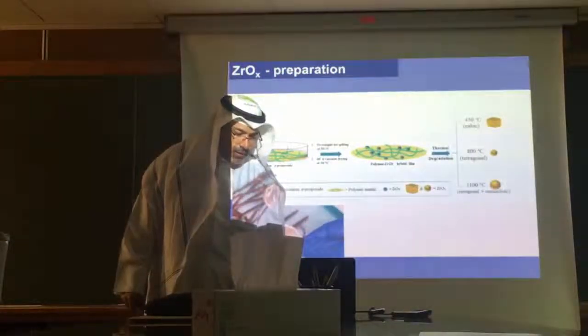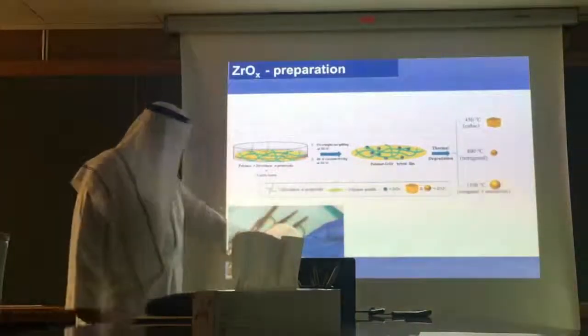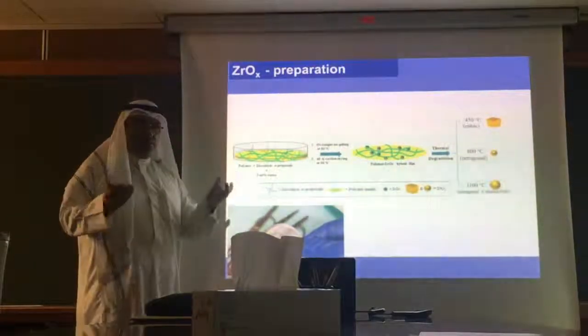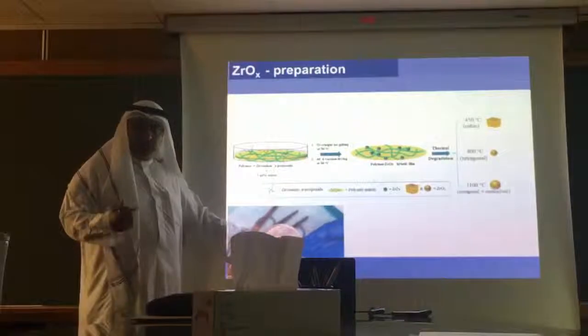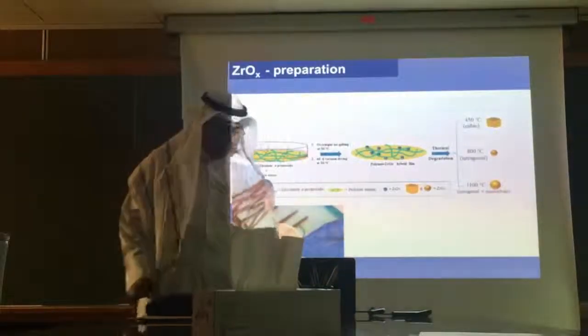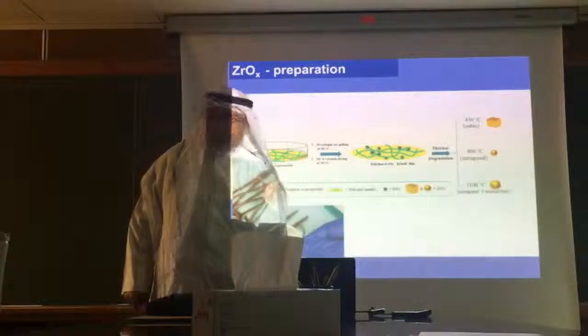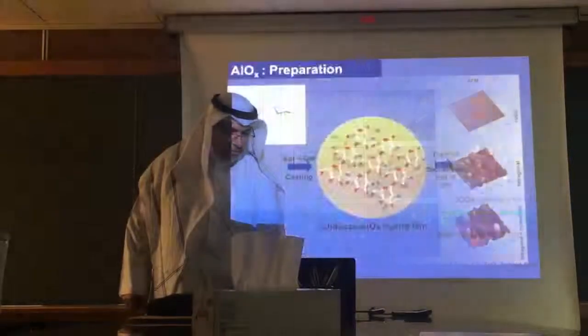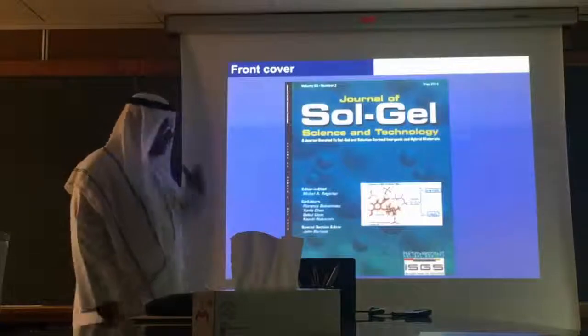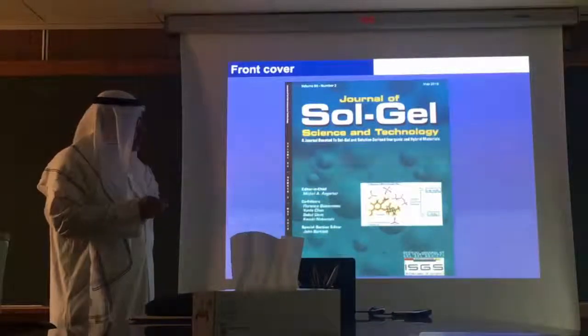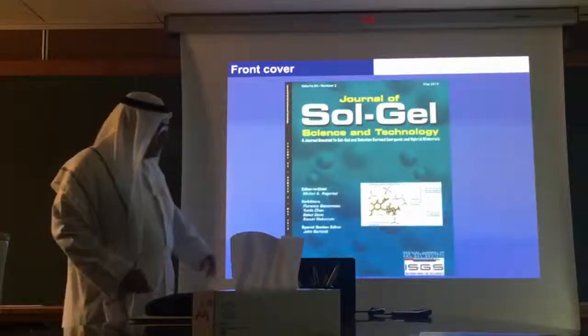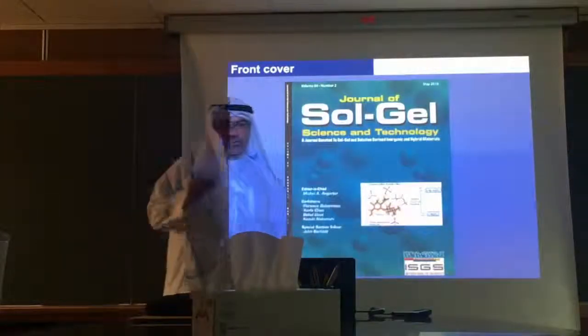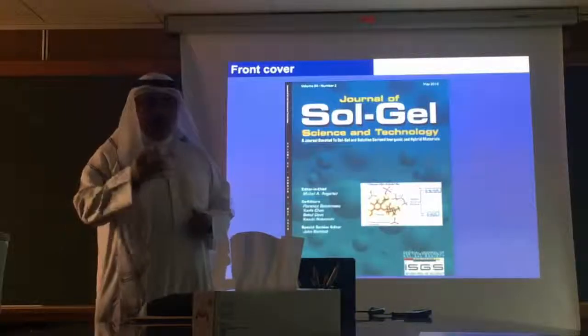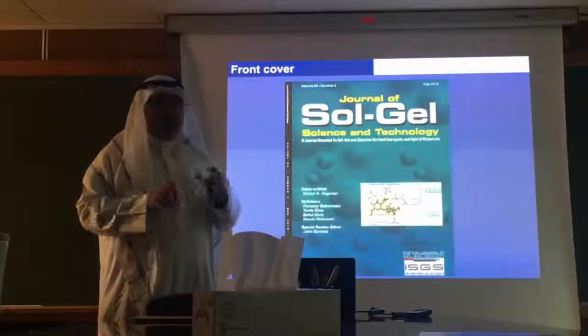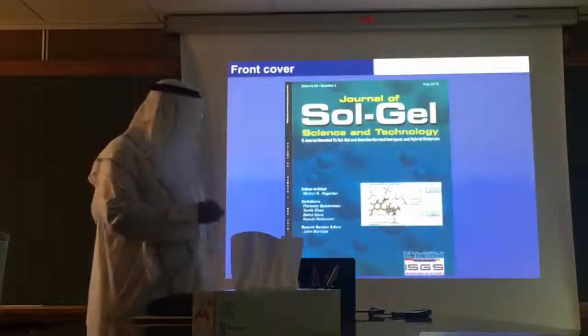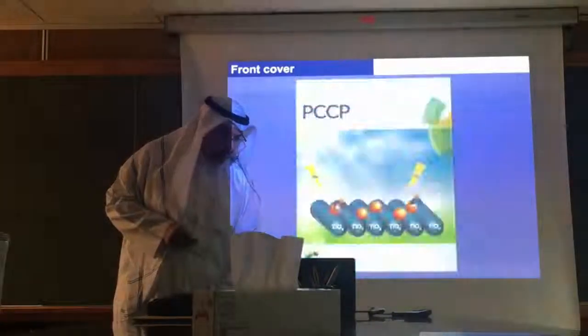This is a way we prepare some of the nanoparticles using film. I prepare a film with my nanoparticles inside it, and then I burn the film. The film is actually from polymer, so you can burn it. When you burn it, you end up with nanoparticles with very strange morphology that caught the attention of one of the journals, and they selected it as the front cover. I submitted the work to the journal Sol-Gel Science and Technology, and the alumina, it's very hard to get a phase called iota. You can get it in terms of other phases, but the iota is very difficult. We get it by this film casting method, and they printed it as the front cover.